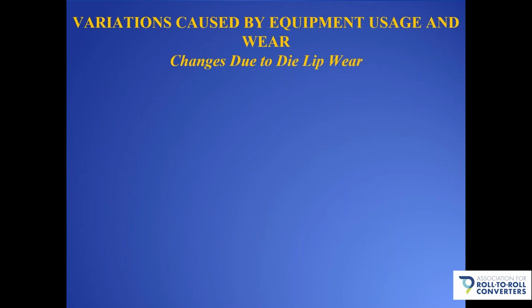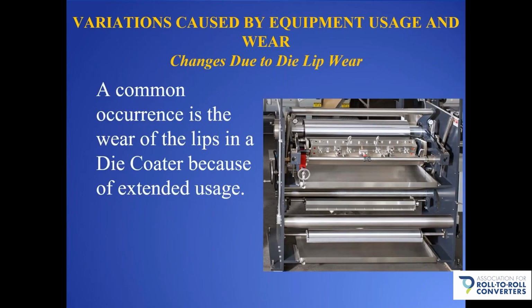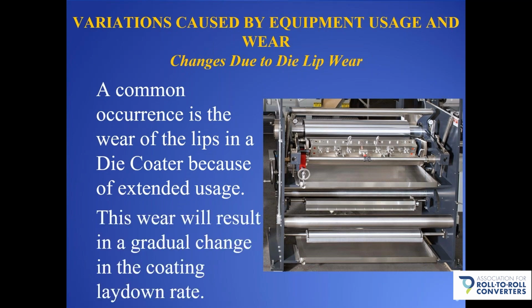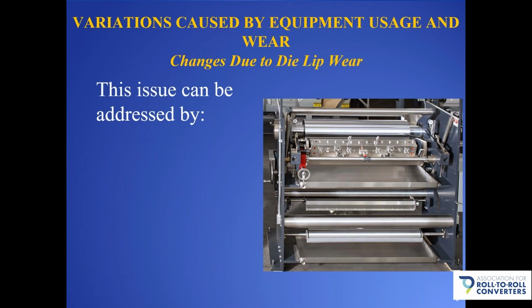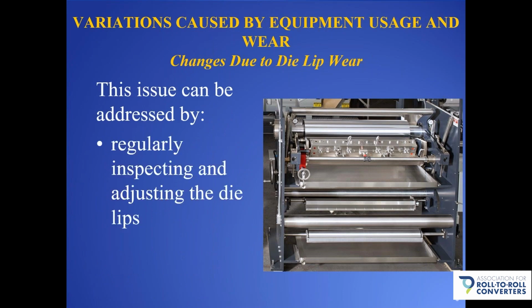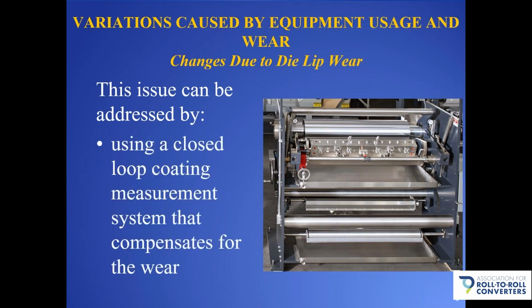Next, let's talk about changes due to die lip wear. So a common occurrence is the wear of the lips in a die as you use it over time. And this wear will result in a gradual change in the coating laydown rate. So how do we address this issue? Well, one of the things you can do is regularly inspect and adjust the die lips, or even replace them as needed. Or again, you can use a closed loop coating measurement system that compensates for this wear, automatically adjusting, in this case, the pump speed to deliver the proper amount of coating.